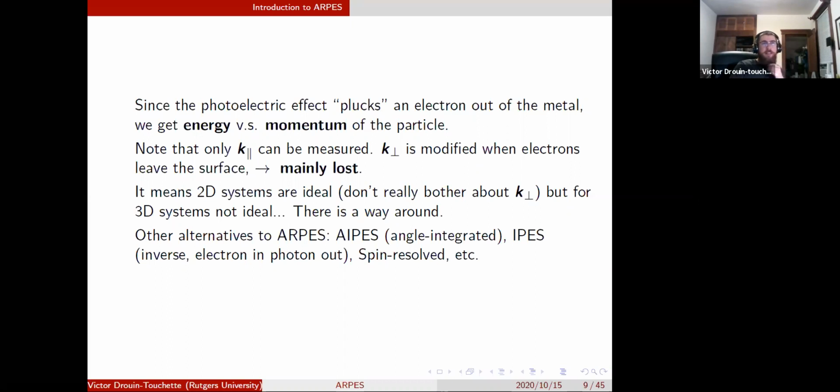So the many-body effect is, basically, ARPES comes in, and essentially what ARPES does is it measures the energy difference between having n electrons in your system and having n-1 electrons in your system for a specific momentum. That's a very abstract way of thinking about it, because what if the band structure and the energy of the electrons were radically changed by effects deep in the material, by correlation effects, so that it would radically change the energy of plucking an electron out, and it doesn't really align with the band structure that you predicted. Those are what I would call many-body effects in this case.